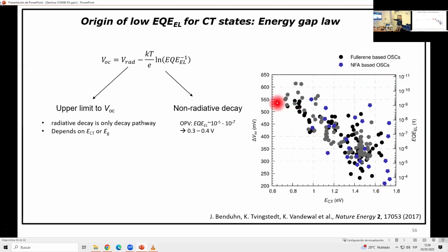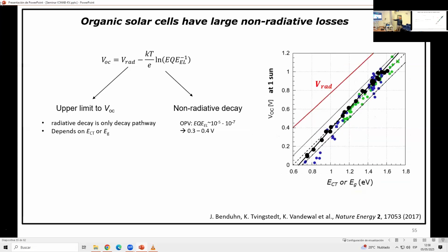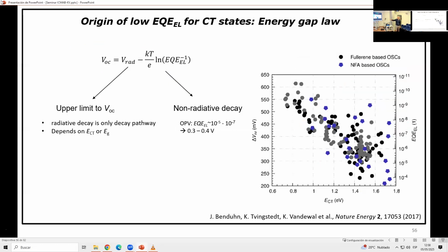Here I plot that difference. This is the difference between the red line and the points. So that line is basically only this extra loss, the one you would think is avoidable, at least in the other technologies, by removing defects. In our case, we see a bit of a trend in that loss. We see that if the gap goes lower, this loss is bigger. So with lower gaps, it's more and more difficult to get higher VOCs. So this non-radiative loss is bigger.